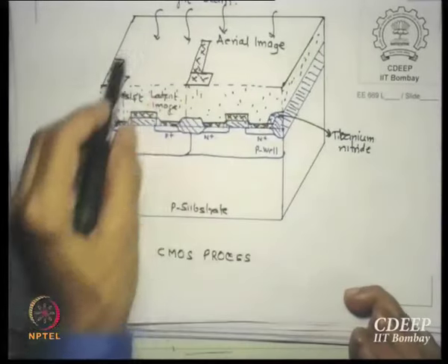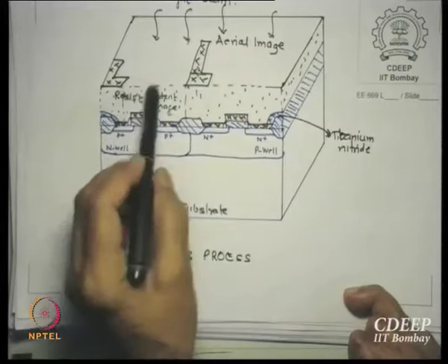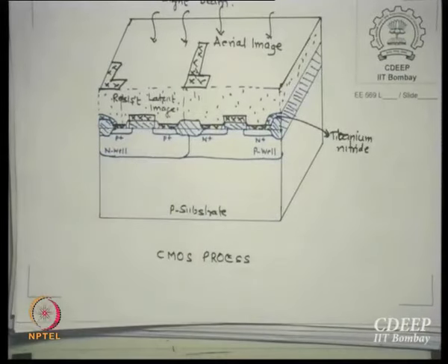From the mask, on the top of the resist, this image is called the aerial image, and inside, below this, is called the latent image, which is the resist image. How close this latent image is to the aerial image, and that is to the mask, is all lithography's expertise. Is that clear? How much thickness should I have so that it goes very well lower down? If it's too low, what can happen? If the thickness is too high, what can happen? These are the choices one has to make. Our ultimate aim is that whatever is in the mask comes identically onto silicon, a one-to-one transfer. How close we can get is our trick of the trade.